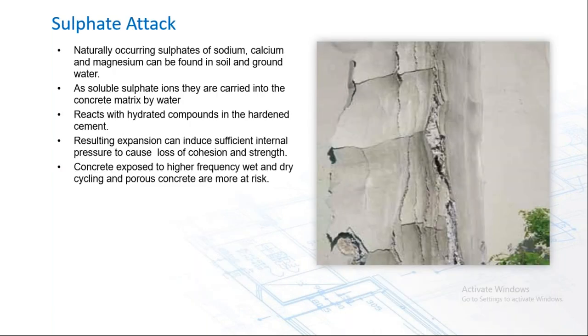Sulfate attack occurs when naturally occurring sulfates of sodium, calcium, magnesium can be found in the soil and groundwater. And as soluble ions, they're carried into the concrete matrix by water. That reacts with the hydrated compounds in the hardened cement and expands, and that can produce sufficient internal pressure that it can cause a loss of cohesion and strength. Concrete exposed to a higher frequency of wet and dry cycling, and porous concrete, is much more at risk.